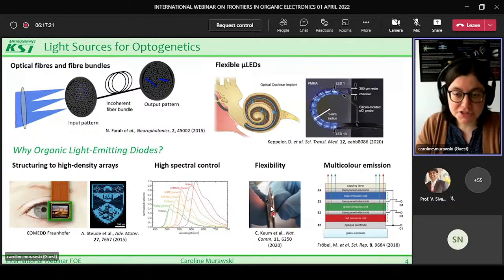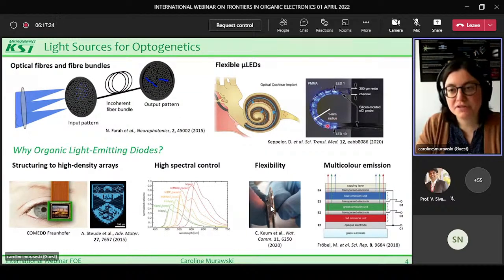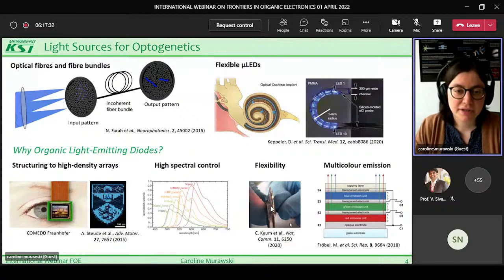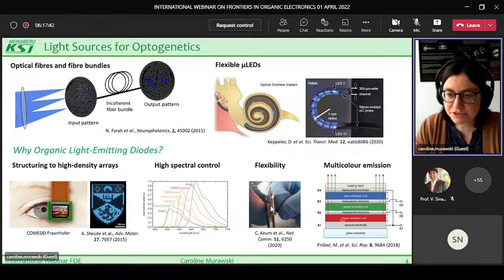And of course, OLEDs can be made highly flexible, not just with 1 millimeter bending radius, but even much more flexible because they can also be made much thinner. And an additional advantage of OLEDs is that it is also possible to emit multiple colors from exactly the same spot. So this example here shows a stacked device with red, green, and blue emission, each operated individually on top of each other, which enables to use the same pixel but for multiple color stimulation. And I will come back to this in my research later in the presentation.